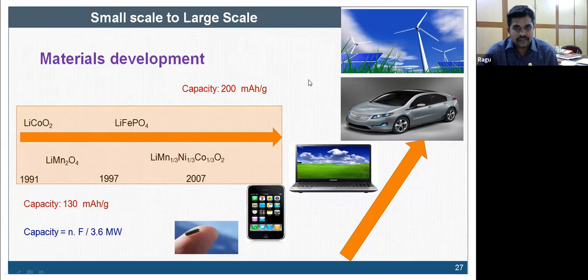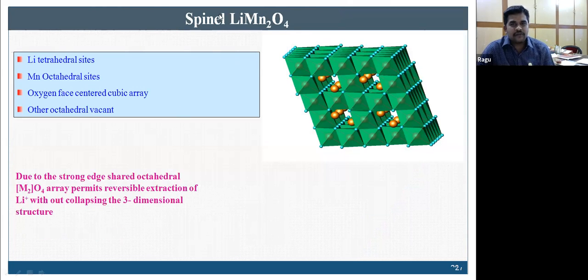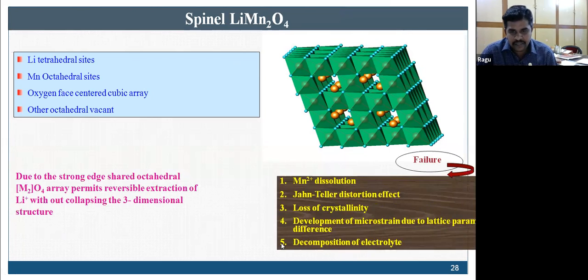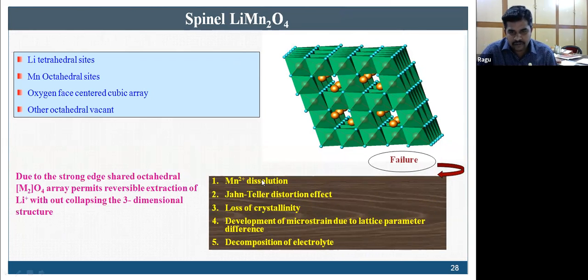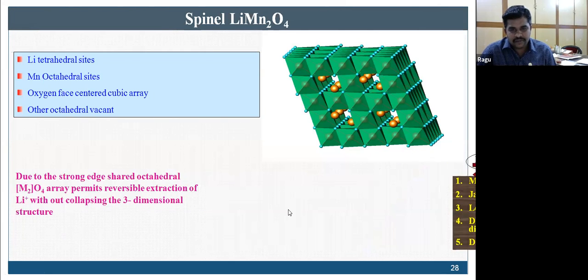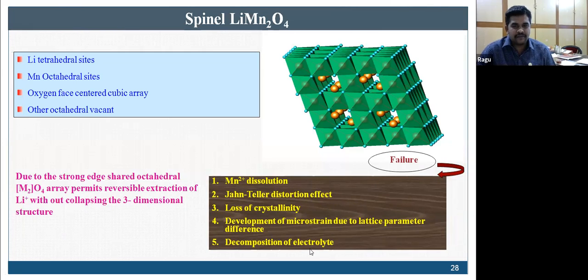Okay. Look at this one, spinel. Though manganese is much cheaper and it has a proper crystal structure for feasible, easy lithium ion extraction and insertion, the problem with that is manganese dissolution. That means active material dissolution in the electrolyte. There is the Jahn-Teller phenomenon, loss of crystallinity, and then the development of microstrain due to the lattice parameter. So these are the failures. At CSIR-CECRI, we would like to highlight one factor, manganese dissolution, considered a major factor causing failure of this battery.